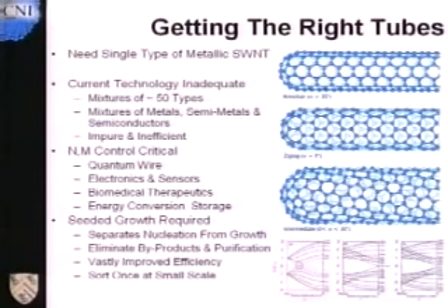This tube up here is what we call an armchair nanotube. It has to do with the structure of the carbon atoms there on the end. This turns out to have a conduction that's like that of a true metal here. It has pretty good carrier density. And here, these other ones are variously semi-metals, which have conductivity similar to that of graphite with a microgap, and the other ones are the direct bandgap semiconductors. So there are about 150 of these types of tubes known, ranging from 1 to 3 nanometers in diameter. And the process that we use now produces about 50 of these right now.